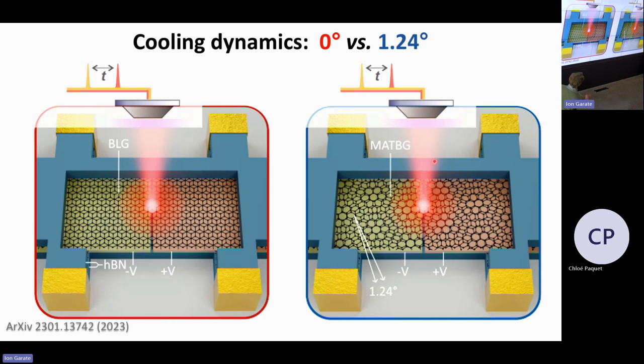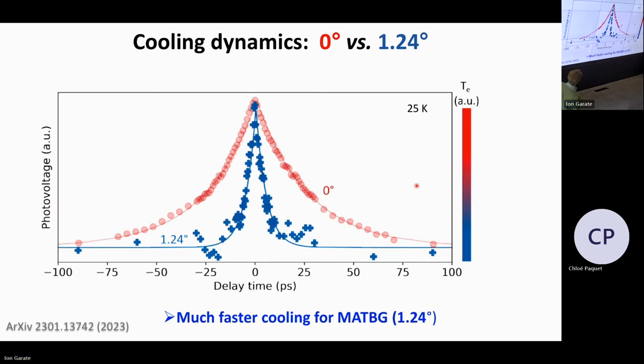Here we have the twisted bilayer graphene, in this case of 1.24 degrees. We have another sample that was around 1.08 degrees, but I don't show it. And then we have these split gates, so we can look at the dynamics. This is one of the main results, so I just show it to you right away. This is at low temperature, 25 Kelvin. So instead of this dip, now I subtract the background and flip it around. What you then see is that the Bernal stacked graphene, in red, is cooling quite slowly. The twisted bilayer graphene is cooling much, much faster. The only thing that's different in these two measurements is that you twisted one layer of the bilayer graphene by 1 degree. So in one case, you get cooling that is several tens of picoseconds.